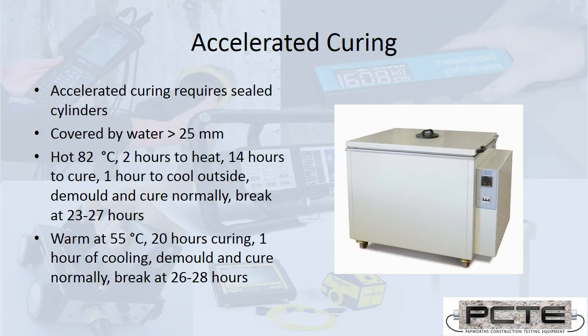Now, as I said, I'm going to quickly explain accelerated curing. The standard defines in particular that when cylinders are going to be placed into a very hot environment, the cylinders need to be heated with a bit of a ramp up. They can't be taken straight from casting and placed in 80 degree heated water. They need to be raised. So if you expect the internal temperature of the concrete to get to a certain point and you're using a match temperature curing system, it's important the cylinders make it into that curing tank before the heat increases. They need to gain heat as the concrete element gains heat, not be shocked by placing in. Also, for warm or hot, there needs to be some amount of time outside to cool before demoulding.